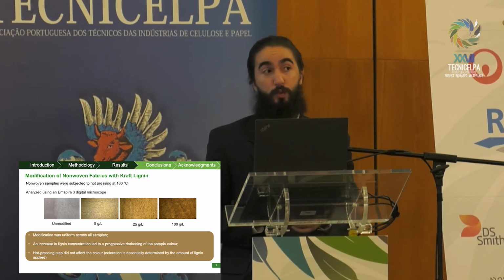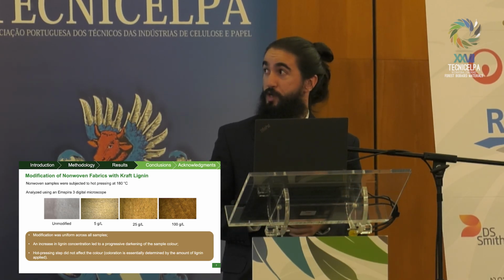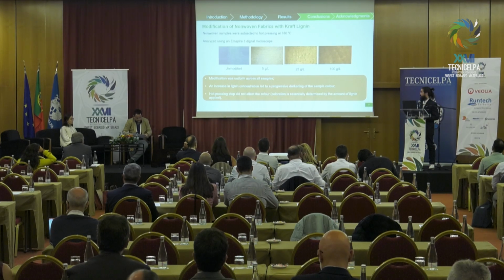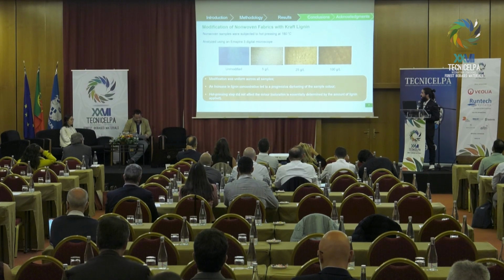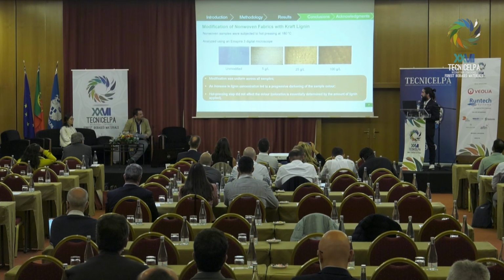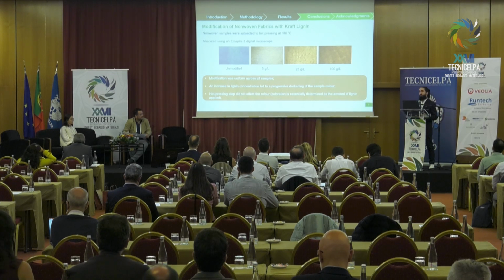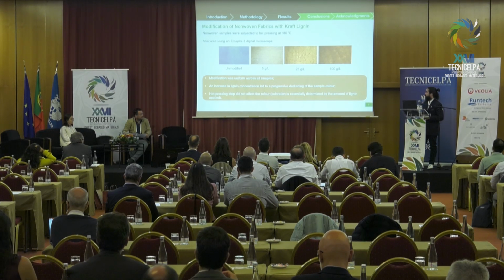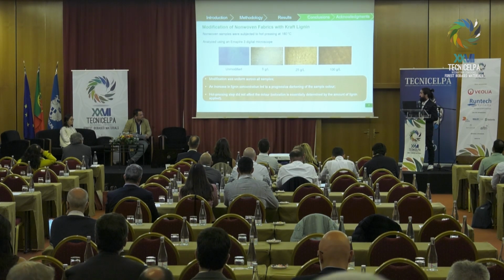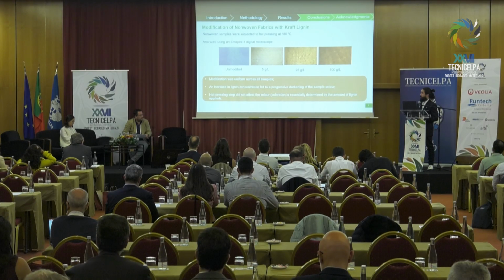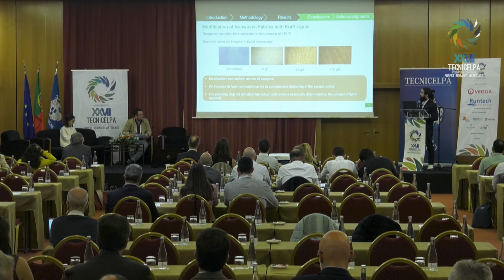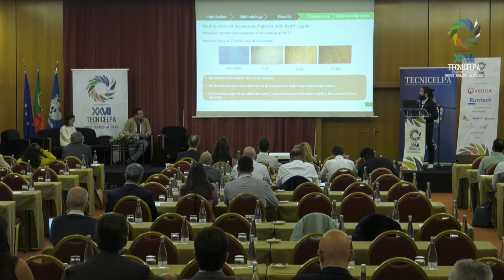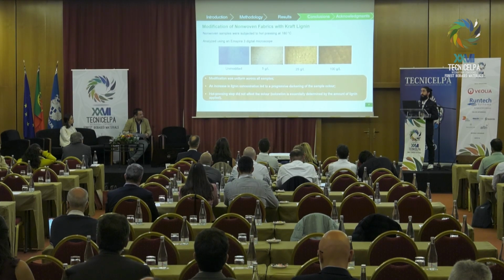Here I present to you the samples that we obtained using three different concentrations. As you can see, the unmodified sample was white, which is the normal color of LYOCELL, and as we increase the concentration of lignin, we get different shades of brown, increasing with the concentration of lignin. These images were obtained with a digital microscope, and we only present the hot pressing at 180 degrees because all the samples, independently of the hot pressure, present the same colors.